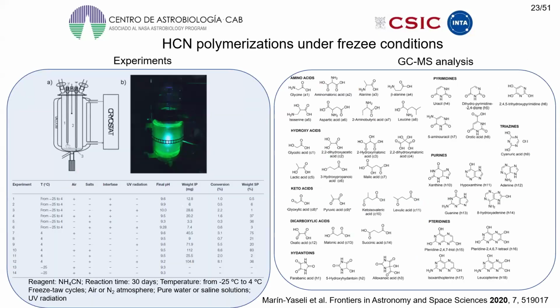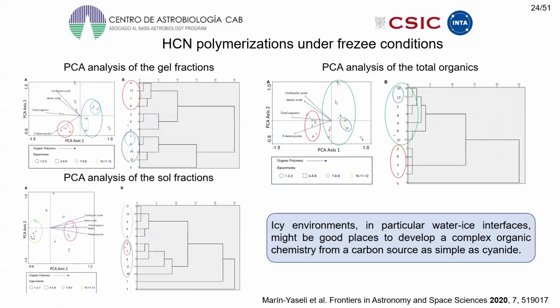Finally, to close this section, one more example of a post-reaction of hydrogen cyanide polymerization, in this case under freezing conditions. Several reactions were carried out using freezing-thaw cycles or by keeping the temperature below 0 degrees Celsius. As in the other cases, the reaction products were analyzed by GC-MS. The statistical analysis of all the analytical data indicated that icy environments, in particular the water-ice interface, may be a good place to develop a complex organic chemistry from one-carbon sources as simple as cyanide. In particular, the formation of carboxylic acids, among them glyoxylic acid, was improved by the presence of freezing-thaw cycles and UV radiation.